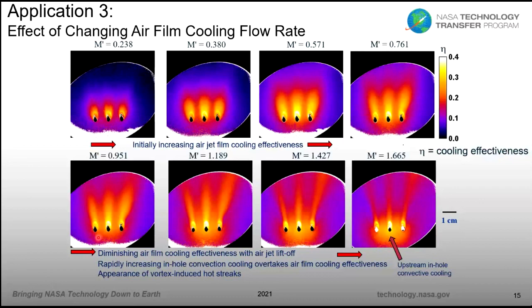Interestingly, though, as you continue to increase the airflow, there's another type of cooling that continues to become more and more effective, and that's in the vicinity of the cooling holes. This is due to what I call in-hole convective cooling. That is, the cooling air cools the sides of the holes, and then by conduction, it cools the area in the vicinity of those holes. And that becomes more effective even though the jets coming out have lost their effect for cooling. But this is all very important in trying to pick conditions for cooling, as well as determining the best geometry for cooling holes and the configuration of cooling hole arrays.